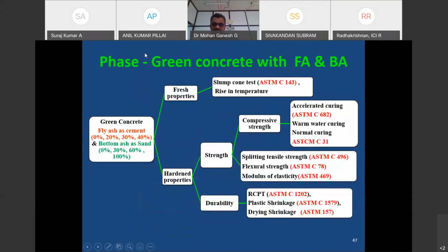The next phase, we have done the green concrete with fly ash and bottom ash. Here, the fly ash is either 0%, that's the control mix, 20%, 30%, and 40%. Again, we have used the bottom ash in place of the sand with 0, 30, 60, and 100. And these are the fresh properties of the concrete. Slump cone test, rise in temperature, we have done it.